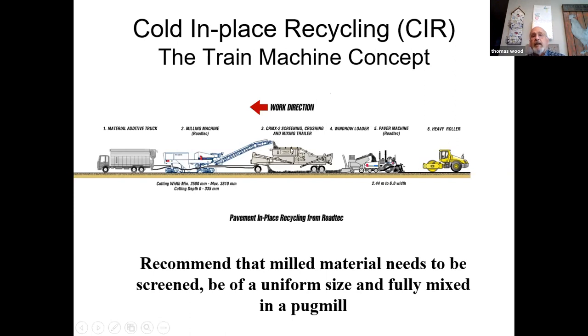Feed it into the machine. There's a screen deck here. Any oversized material goes down to a hammer mill or a crusher. It's recrushed and run back up over the screens. The material that's the proper size falls onto a belt, comes up to a weigh scale, is weighed, and a computer meters in the additives, whether it's a liquid system like emulsion or foamed asphalt, or a dry system like cement or lime.